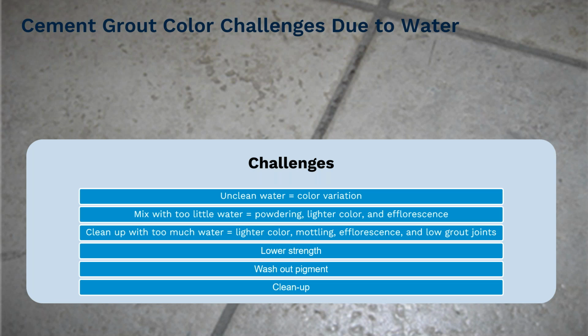If you clean up with too much water, so you have it installed, you're all done, and you clean up with too much water, you can wash out some of that pigment so it can become a lighter color, or you might have some low grout joints. It can cause it to have a lower strength, as well as make cleanup a little bit harder.